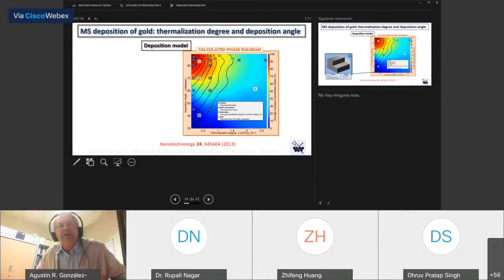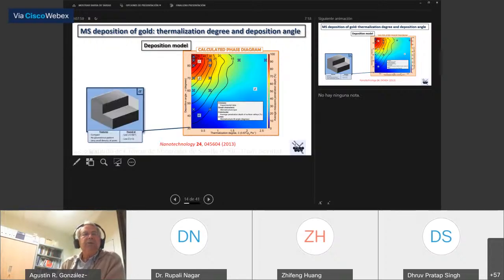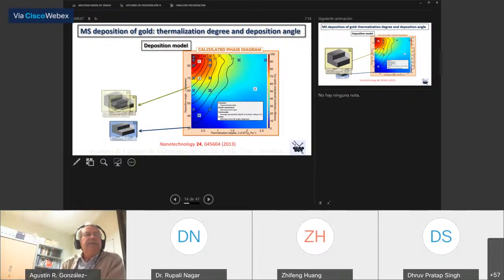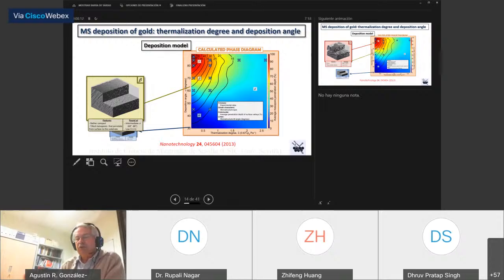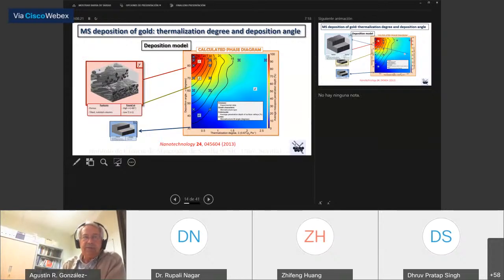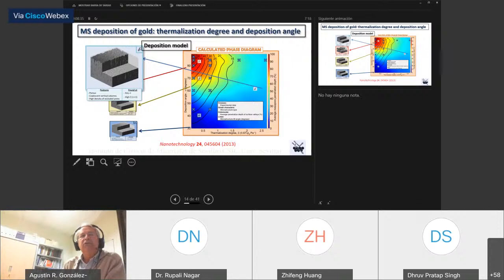This is a work already a little bit old, some years ago, where we studied the effect of the thermalization degree of the particles and the deposition angle during an oblique angle deposition experiment using gold. And we produced a kind of calculated phase diagram. We also used a deposition model, and we discovered that depending on the situation in this diagram, it would be possible to get a compact structure like this one. A structure where in this area we have pores which are moving from the substrate up to the surface, but not yet nanorods. Or in this area, we have formation of nanorods. So it's very critical in this phase diagram moving through the thermalization degree and through the deposition angle. Well, in this area, we get the typical Thornton model structure, typical of magnetron sputtering deposition.